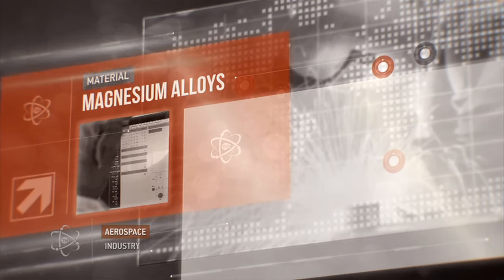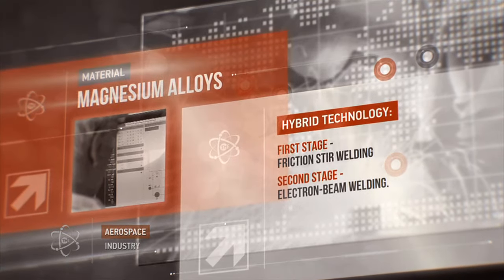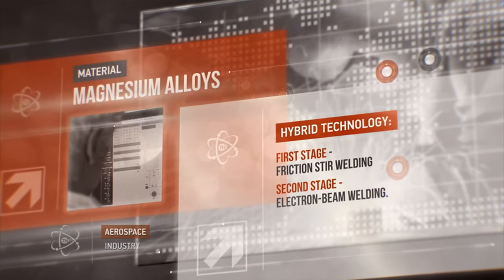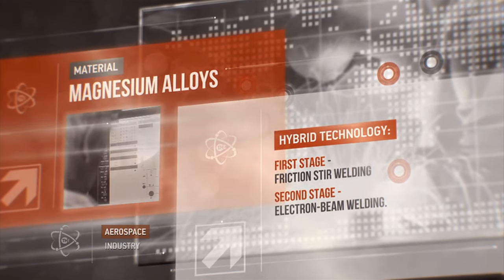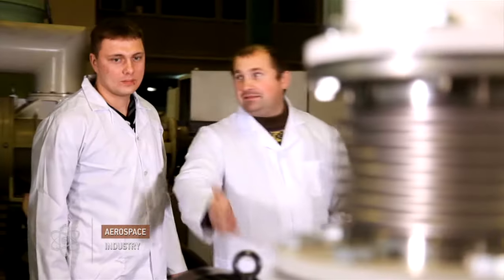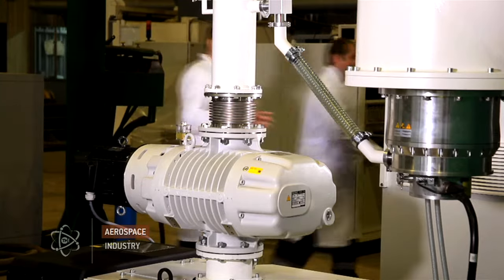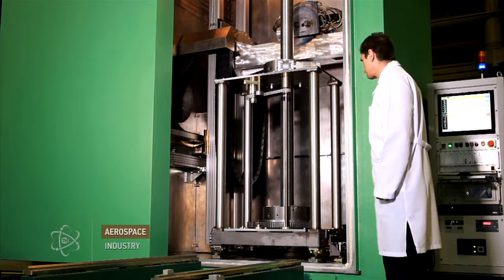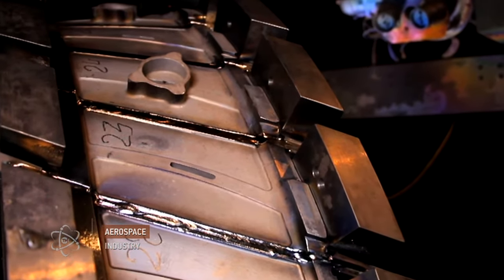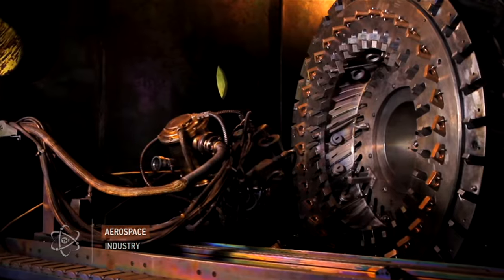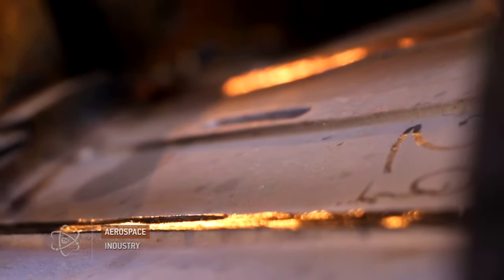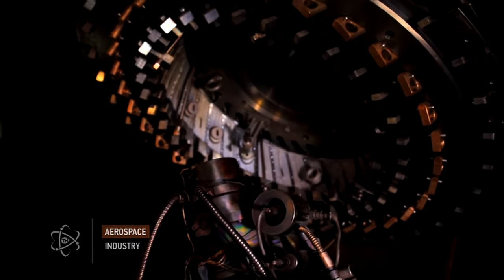The B.E.Paton Institute has developed a hybrid technique for connecting this material. The first stage is friction stir welding, and the next stage is electron-beam welding. Thanks to pre-treatment of welded edges by stir friction, cracks and other defects are avoided, and welded joints become almost twice stronger, with their plasticity and impact resistance enhanced as well. This technology has been developed for rehabilitation of intermediate casings of aircraft engines by welding in a 6 mm thick rectangular insert in the damaged area.